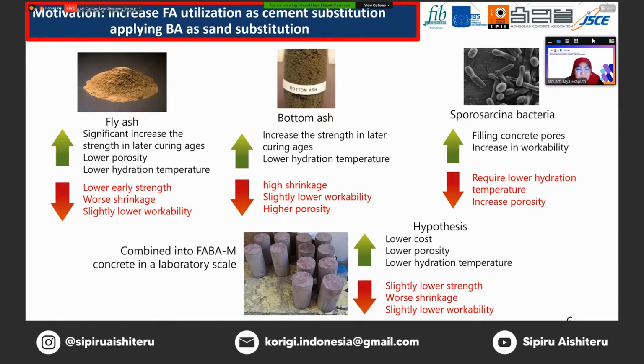We use these microbes, and it is also found that the microbes created gas as the metabolism product during the casting. So it increased the workability of the concrete during casting. However, it requires lower hydration temperature.